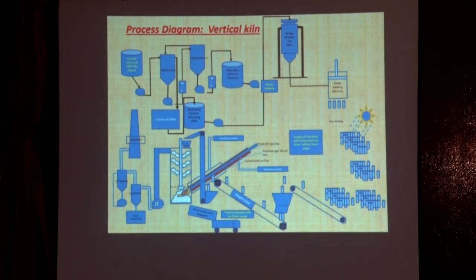It was running at 80%, and you will see the fuel has been reduced and the ID fan RPM has been reduced to keep the heat in the burning section. You will see the purity has drastically dropped, down to 60%. Then it takes another 4 hours to bring it back to 80% purity.